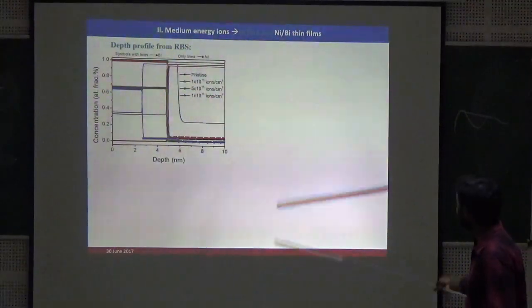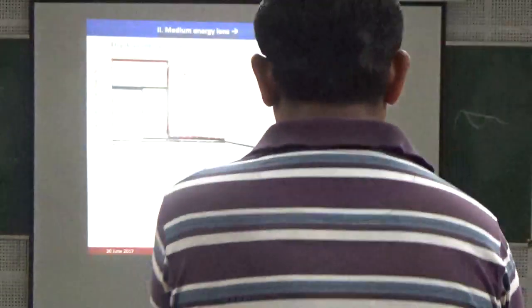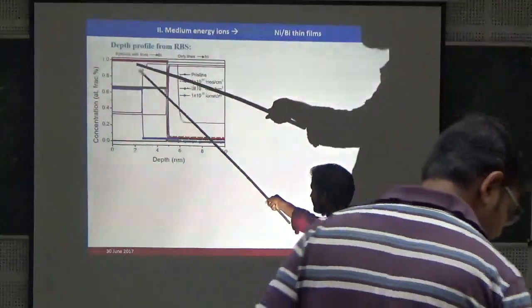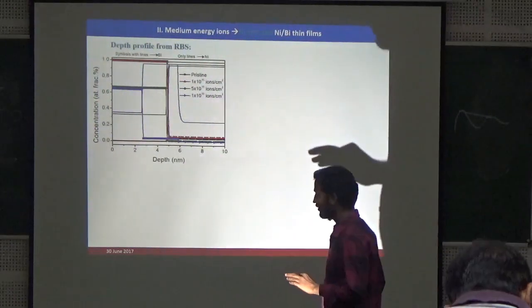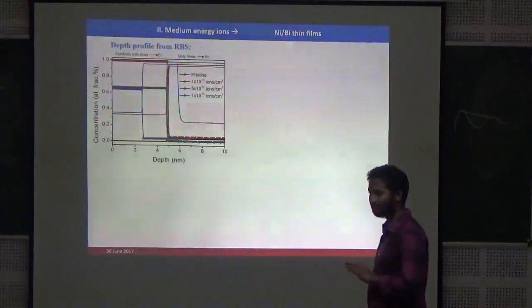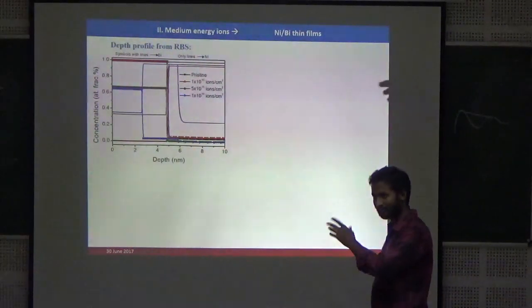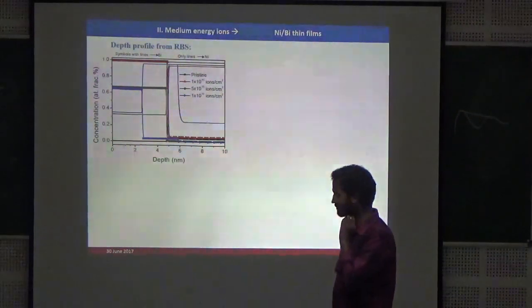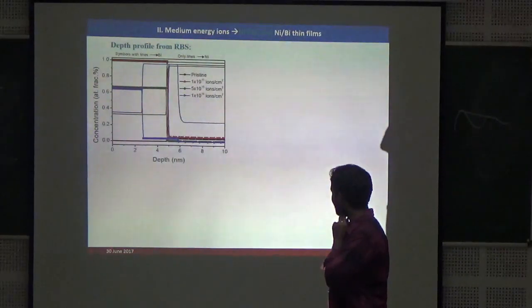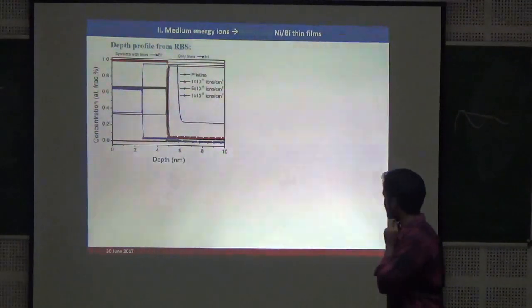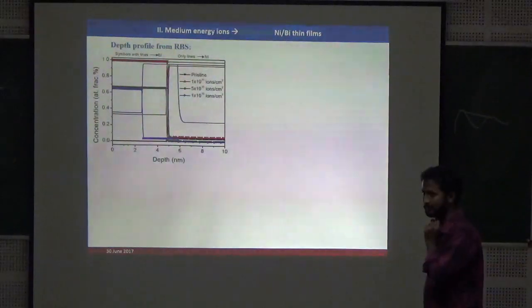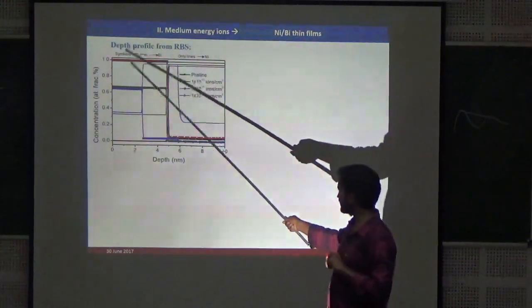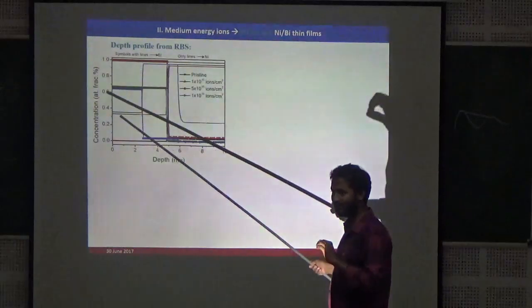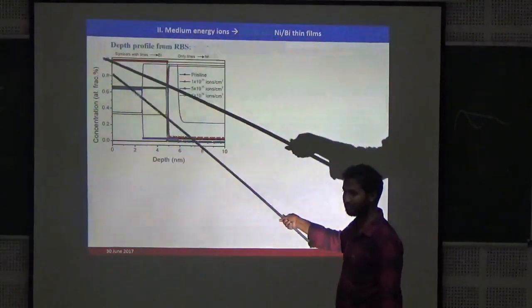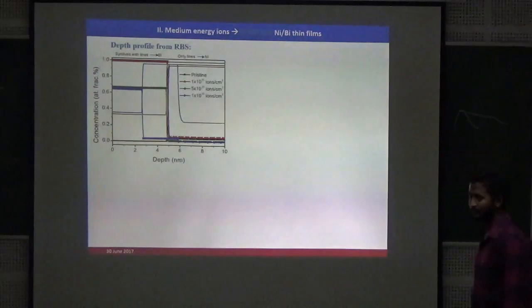So here it is, the pristine sample. This is the bismuth layer profile. This is nickel, at almost 0.98 atomic fraction. Even in this layer we see nickel diffusion into bismuth. If you expand the central line, you will see it is around 1 to 2 nanometer, within a nanometer. Even in this layer there is nickel, but it is very less. Nickel is also there in this layer. Okay, so 1 to 2 nanometer is already interdiffused.